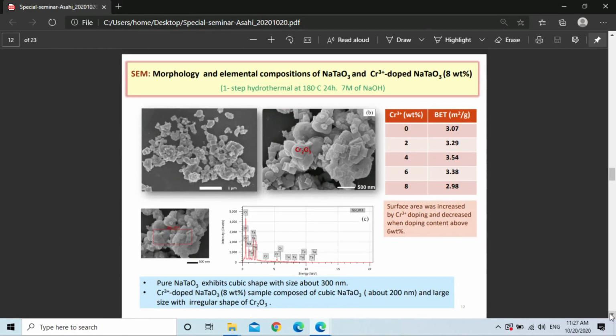The SEM observations show the morphology of sodium tantalate. Pure sodium tantalate has a cubic-like morphology, but on the right hand, when we dope a higher amount, we can see a mixed morphology of sodium tantalate and chromium oxide. This confirms the XRD result, and the EDS elemental analysis confirmed the existence of only tantalum, sodium, and chromium in the sample. BET surface area shows that when we dope with chromium ion, the surface area slightly increased. But when a higher amount of chromium ion was doped, the surface area decreased because of the precipitation of large particles of chromium oxide.